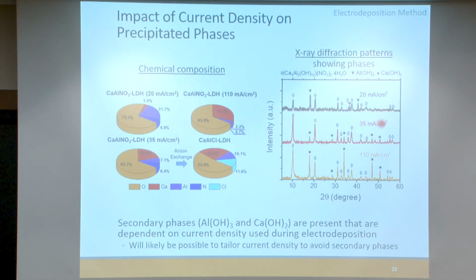If you increase the current density for synthesis, you end up with your layered double hydroxide, but now the secondary phase is calcium hydroxide. And so what that means is during the deposition, using this current density, that the amount of hydroxides that were being produced were high enough so that the pH was above the pH at which calcium hydroxide precipitates. And so even higher current density shows this calcium hydroxide forming as well. So it's likely possible, and this is what we're still working on, to tailor current density to avoid formation of these secondary phases. This is just kind of a first approach of the deposition by changing the current density here.